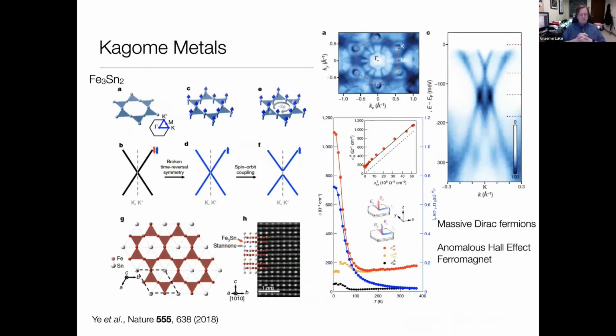So there's been some recent effort, in the last little while, to look at Kagome metals, and that's going to be the subject of much of what I'm going to tell you about today. One of the earliest interesting examples of this was the material Fe3Sn2, which has a structure here, showing the irons on the lattice, and you see the irons form this Kagome pattern. This material actually becomes a ferromagnet. One of the peculiarities about the Kagome lattice is that you get a linear dispersion of the electron energy as a function of wave vector.